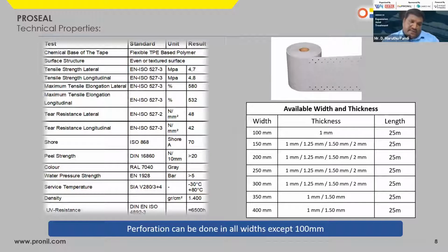And for water pressure, we can even fix it on reservoirs and dams, and it can stand 5 bar water pressure. Service temperature is -30 to 80, and density is 1.4, and it is UV resistant, tested to European DIN standards. And we have various widths in the tape, like 100 mm, 150 mm, 200, 250 up to 400. Now we have started producing up to 700 mm width also, and we have thickness of 1 mm to 2 mm and a length of 25 meters. And perforations, we are doing for all except 100 mm. Perforation is nothing but the holes on the sides of the tape.